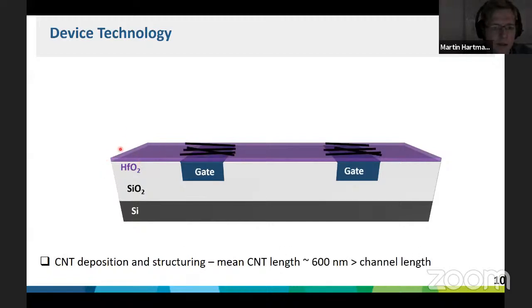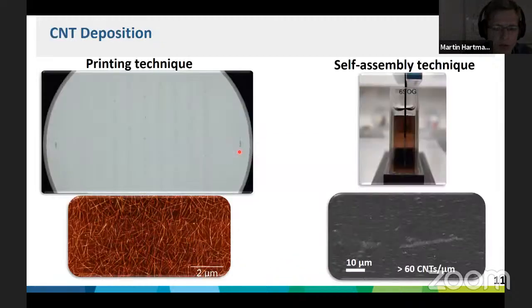And the next thing is the CNT deposition and the structuring of the CNTs. And we have different approaches to deposit the CNTs. One approach is a printing-like technique. There we can print CNTs with a rather random orientation and with different densities. So we can define the density here by our process parameters. And here it's shown that the CNTs are printed in thin lines over the entire 8-inch wafer. So we can print them wherever we want them, but not necessarily on the entire wafer, just on these locations where we really need it.